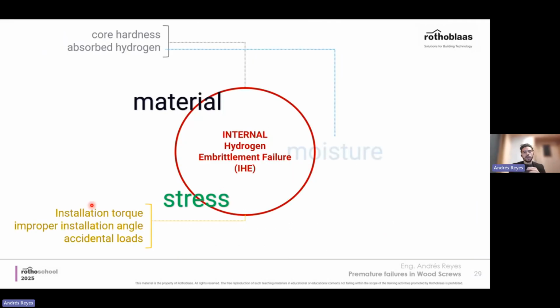Okay, perfect. So, as I said before, and as you've now seen, for a failure caused by internal hydrogen embrittlement, moisture doesn't need to be there, because the hydrogen is absorbed in the manufacturing process. So it's more a material condition right after the production process. But what's necessary as well for failure is stress. Of course, as I said before, the screw doesn't break just by taking it. So a minimum stress needs to be present, and in general it comes from installation torque, an improper installation angle, or accidental loads. The higher the stress, the higher the possibility of a hydrogen embrittlement failure if the material conditions are met. And it happens, as I said before, from hours to days after installation.